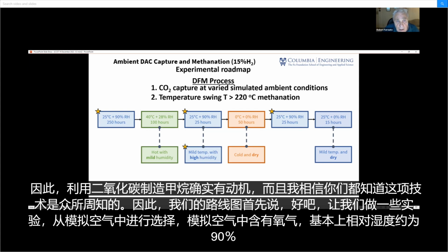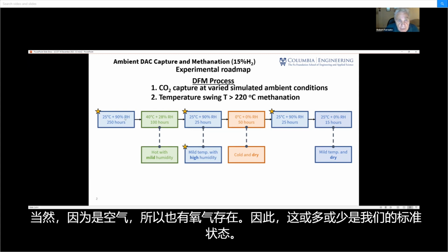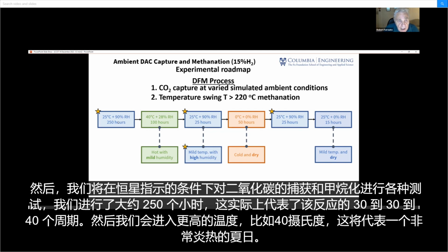So there is a real incentive to making methane from CO2, and the technology, as I'm sure you all know, is fairly well known. So our roadmap was to begin by saying, okay, let's do some experiments where we simply do adsorption from simulated air, which contains oxygen and essentially relative humidity here of about 90%. Naturally, because it's air, there's oxygen present as well. So that's more or less our standard state. And we would then do a variety of testing for CO2 capture and methanation at a condition indicated here by the star. And we did that for about 250 hours, which represented literally 30 to 40 cycles of that reaction.